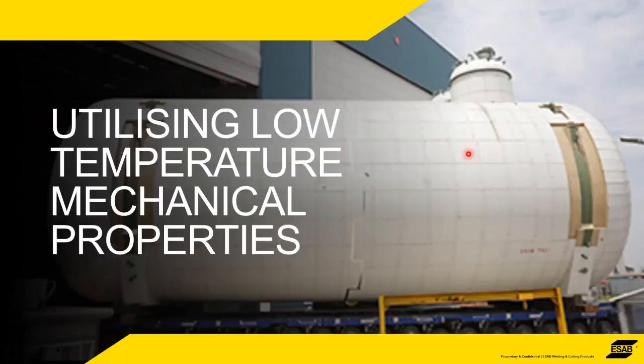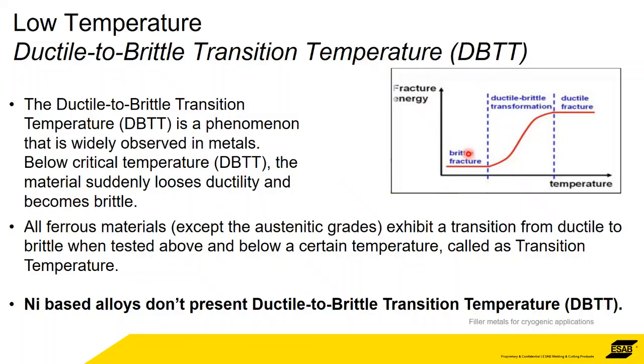So utilizing low temperature mechanical properties, something that always needs to be taken into consideration is this phenomenon called ductile to brittle transition temperature, DBTT. It's a phenomenon that's observed in most metals, and as a design engineer and as a welding engineer, you need to be aware of it. Basically, what it's saying is that at room temperature, what could be perfectly acceptable with a nice ductile structure, once you start to cool it down, as the temperature is reduced, goes through this transition from being ductile to being very brittle.